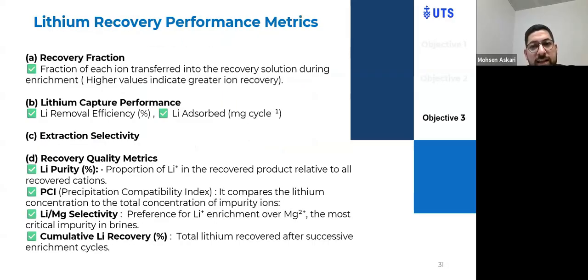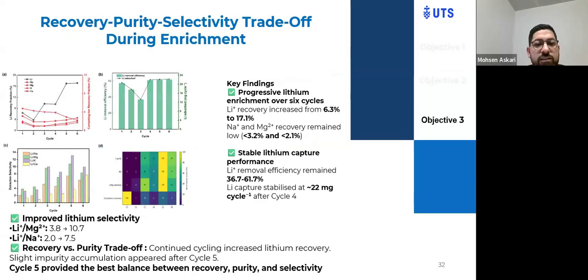For the next experiments, we used the recovery fraction, lithium capture performance, extraction selectivity, and recovery quality metrics. We try to balance these parameters and trade them off. The result shows that progressive lithium enrichment over 6 cycles is possible.